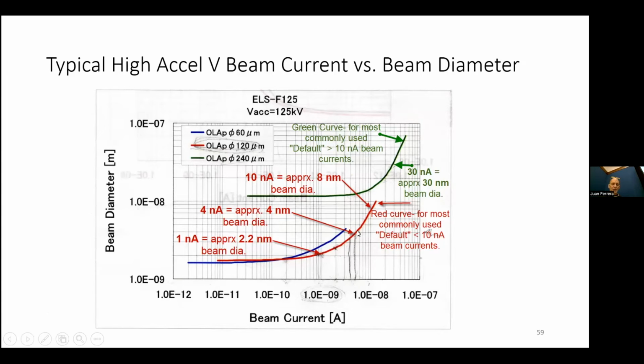This is the red, this is the smaller aperture, and we can go from like 100 picoamps to 10 nanoamps on this. So for a range from like here at this inflection point up to maybe here, basically from about 2 nanoamps up to about 50 nanoamps or so, it turns out on our tool anyway, but on some other tools it's similar, the beam diameter in nanometers is equal to the beam current in nanoamps.